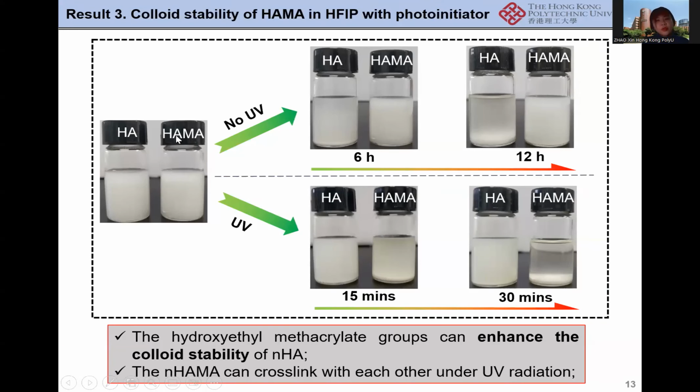So this is the C=C plus hydroxyapatite nanoparticles, and this is the naked hydroxyapatite nanoparticles. If we don't cross-link them and just mix them with the organic solvent, we can see that the C=C methacrylated hydroxyapatite nanoparticles, after a very long incubation with the organic solvent, do not sediment to the bottom, because the interaction between the nanoparticles is very big, which increases their colloidal stability.